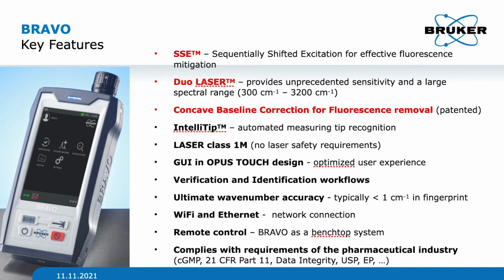Now, when we developed the Bravo, one of the things we really wanted to bring to the market was a tool that could actually get you around fluorescence. And so we've done that three ways. One is that, well, let's just use a couple of different lasers at the same time. So we have a duo laser configuration where we're using two different lasers. So if the electronic transition for fluorescence is at one wavelength, we can either go above or below that transition many times to actually get around the fluorescence.